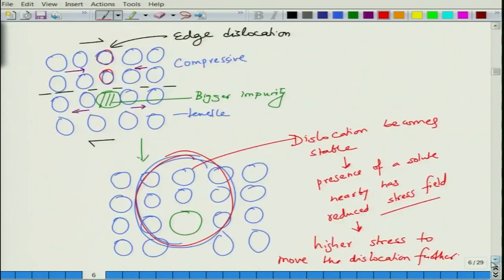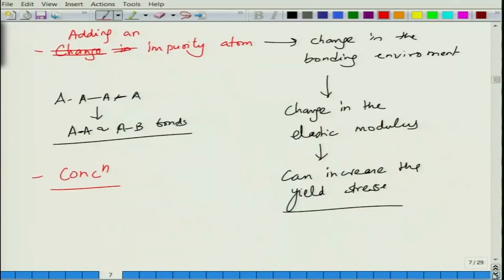So basically what we are saying is that addition of impurity atoms, substitution or interstitial impurity, can stabilize a dislocation by compensating the stress fields, making the dislocation more stable, and hence you will require larger stress to move it, depending upon its size, of course. Then adding an impurity atom also causes a change in the bonding environment from AA to AB kind of bonds, and if the AB bonds are stronger than AA bonds, then the elastic modulus will change, and then you can change the yield stress. And of course it depends how much you add, how much solute atom you add to the host.